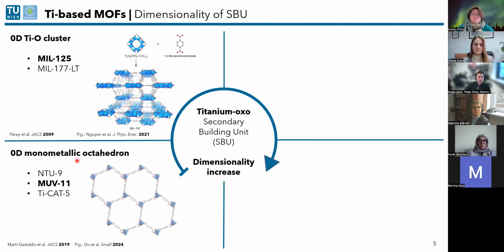But we can also have a titanium oxo cluster. Instead of just one titanium atom or titanium center, we can have a cluster of many of them. And you have also some bridging oxygens. And these bridging oxygens are also very important for stabilizing these titanium 3+ charges. So this is also done with carboxylates.